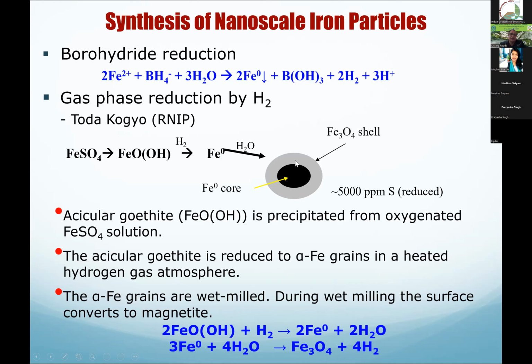Oxygenated iron sulfate solution, and then the goethite is reduced to alpha iron grains in a heated hydrogen gas atmosphere, and then those iron grains are wet milled to the size that you want. During the wet milling, the surface converts to magnetite. So these are the reactions that happen. Basically, the goethite is converted into zero valent iron particles, and if zero valent iron particles are mixed with water, then you will have Fe3O4. That's magnetite.